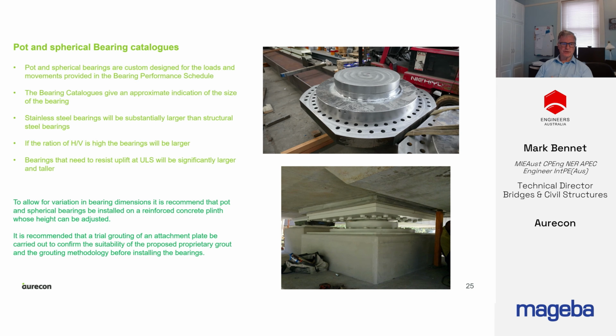To allow for variation in bearing dimensions, it is recommended that pot and spherical bearings be installed on a reinforced concrete plinth whose height can be adjusted. Also, it's recommended that a trial grouting of an attachment plate be carried out to confirm the suitability of the proprietary grout and the grouting methodology before installing the bearings.